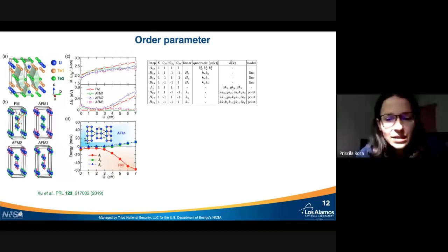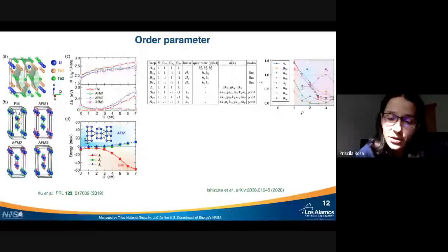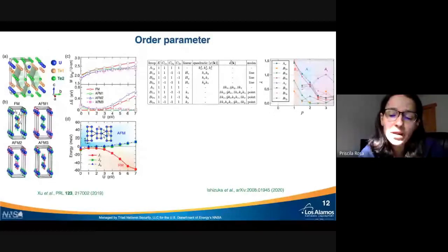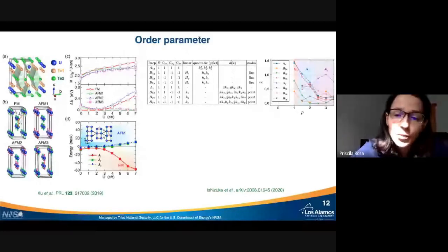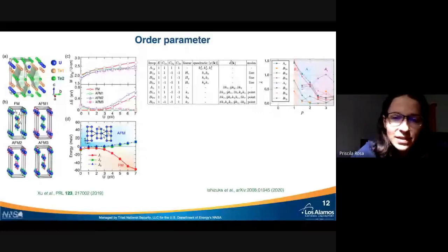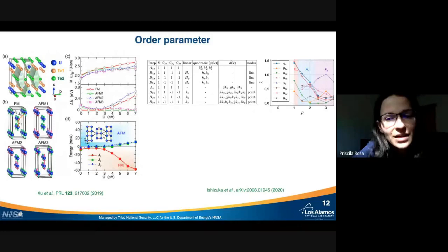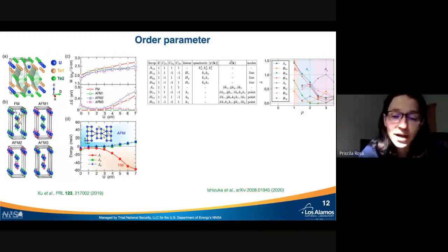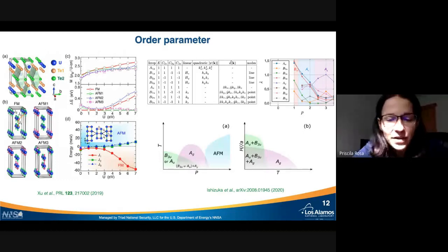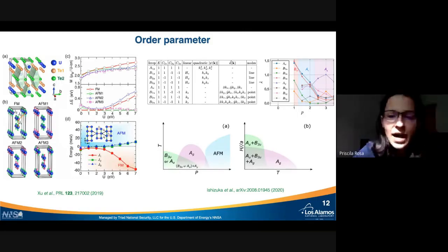And it's interesting that this very recent theoretical result, that took into account our data that I just showed you, actually shows that under pressure, the components here, the irreducible representations, change. So they can go from something that's more spin triplet-like to something that has a singlet component and then has a mixed order parameter, which is quite remarkable. Going a little bit further in this, one could also envision that magnetism will show up at higher pressures. Same thing with field, temperature versus field, because we have two different irreducible representations. They have different field dependencies, and here is one possibility for their behavior.